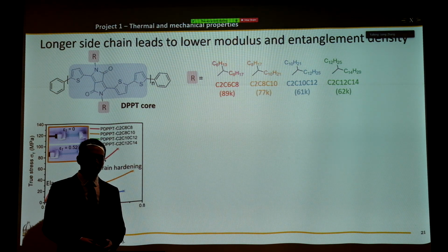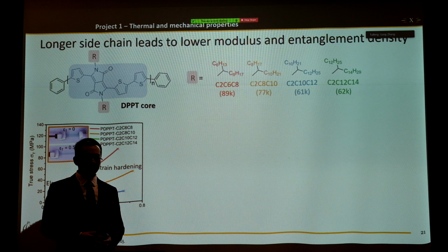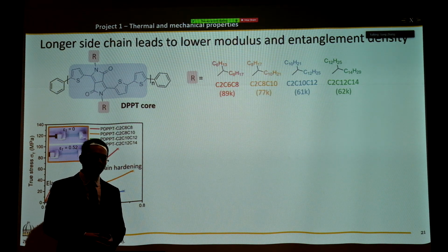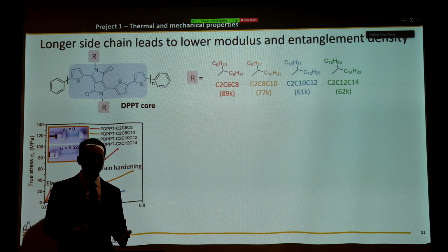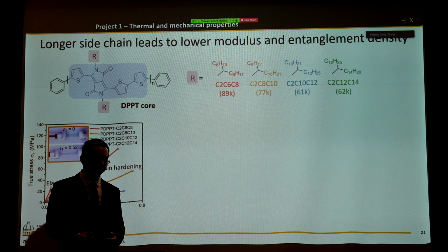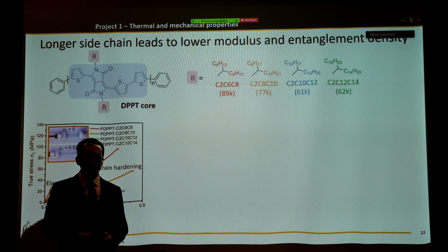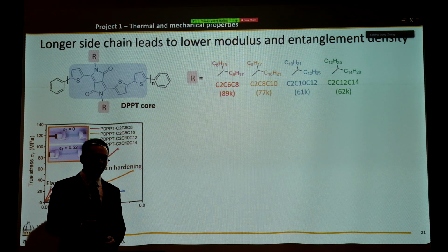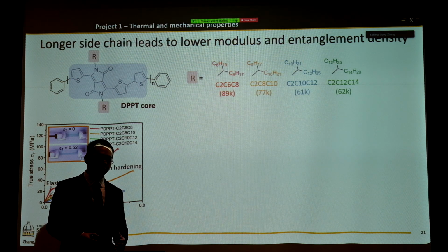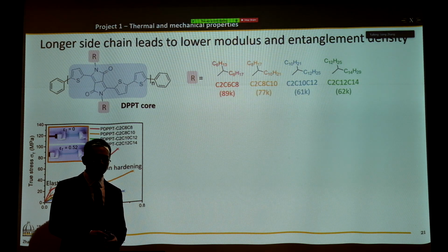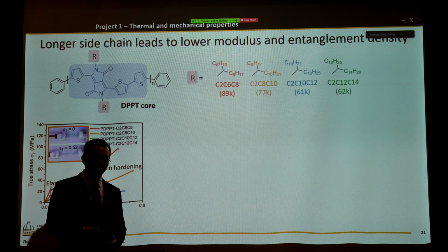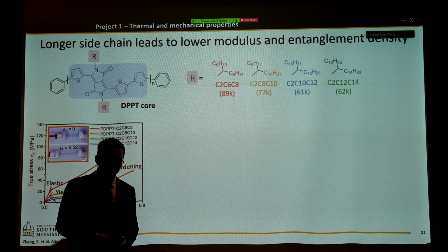stress-strain curve where obviously the elastic modulus is dropping with longer polymer side chain length. And secondly, if you see the crack onset strain, again, it does not show obvious structural effect, and we believe molecular weight should be the key. And thirdly, it is kind of weird that the strain hardening behavior at large strain is very different. As shown in the red curve, which represents the shorter side chain length, the slope seems to be much higher when compared with C2C12C14, as shown in the blue curve.